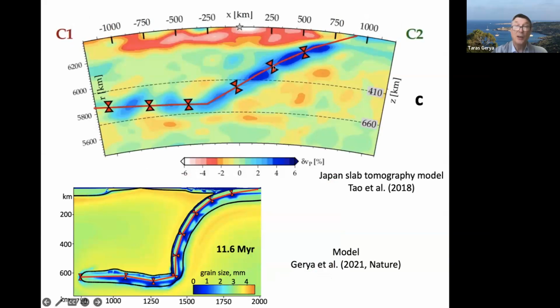When I saw these blobby slabs in the past, I was always joking when speaking to mantle tomography people that you are doing something wrong with your mantle tomography, because you see this blobby slab behavior, while in models we see very smooth and nicely distributed slabs without any internal heterogeneities in their structure. But in reality, I was wrong, and these people were right, because indeed the intensity of seismic velocity anomalies inside slabs can be very strongly dependent on the intensity of grain size reduction, and the periodicity of this segmentation within slabs is quite comparable with the prediction from models with corresponding plate ages.